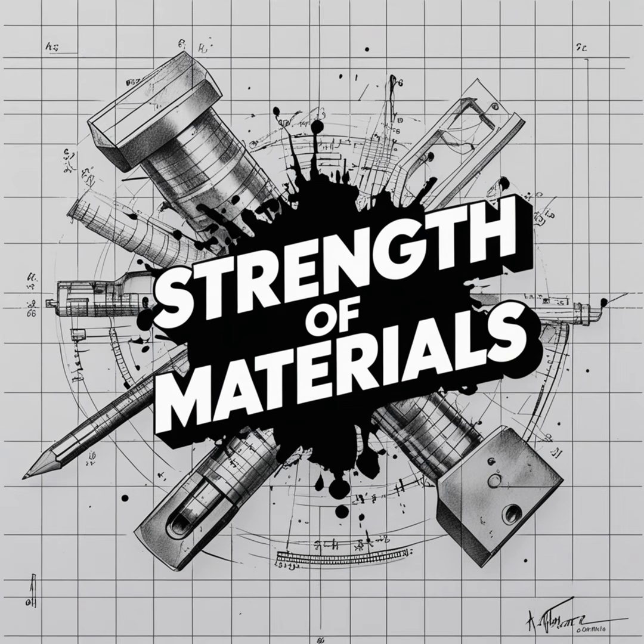So the holy grail of fatigue prevention is to induce a permanent state of residual compressive stress on the outer surface of a component. So the goal is to permanently squeeze the outside layer of the metal so that even when the machine is running and pulling on the part, the net force at the surface is still pushing inward, keeping the crack shut. Exactly. You beat the tension by starting with compression.